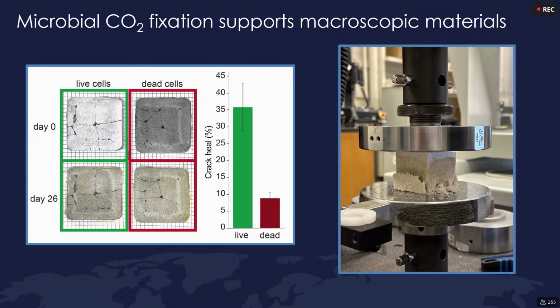And we can vary that and actually speed up the process by just increasing our weight percent. So this is with 0.1 weight percent of microbes to cement mix. We can go up to 2% without negatively impacting the overall compression strength of the cement, which is what we want, right? If we're starting to sacrifice the overall strength of the cement, nobody's going to want to use it. So we need to maintain the original properties, but we can also speed up this process.